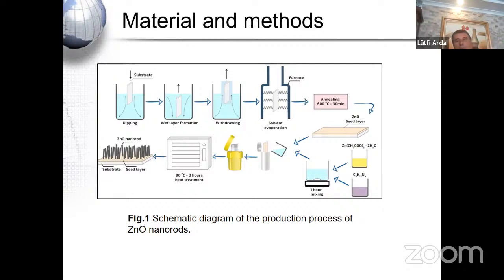Okay. How can we fabricate the nanorod on the zinc oxide seed layer? First, we clean the glass substrate using ethanol and deionized water. Then we use the sol-gel method to prepare the solution for the seed layer. The seed layer was zinc oxide. That means we use zinc acetate as a precursor material, methanol was used as a solvent, and monoethanolamine was used as a stabilizer. Then all this material was placed in a beaker, and we stirred it until we got a transparent solution.